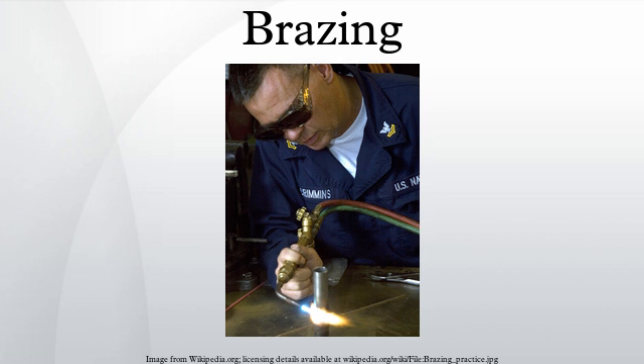Cobalt alloys. Good high temperature corrosion resistance, possible alternative to Ag-Pd brazes. Low workability at low temperatures, preforms prepared by rapid solidification. Al-Si, for brazing aluminium. Active alloys, containing active metals, for example titanium or vanadium. Used for brazing non-metallic materials, for example graphite or ceramics.